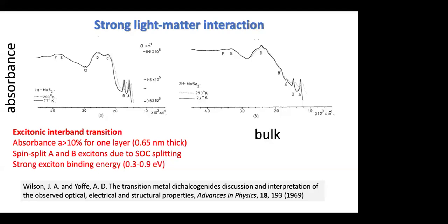In bulk, you have the energy gap. What is important is that in those materials, light couples very strongly to matter, and you can see characteristic absorption spectra for molybdenum disulfide or molybdenum diselenide at 77 K, but also at room temperature. And you can see that also at room temperature, there are very clearly distinguished excitonic peaks. Excitons do exist even at room temperature, which means that the exciton binding energy is really high in those materials. I will talk about this later.